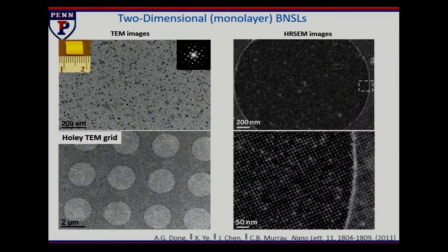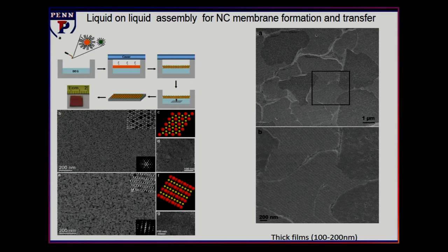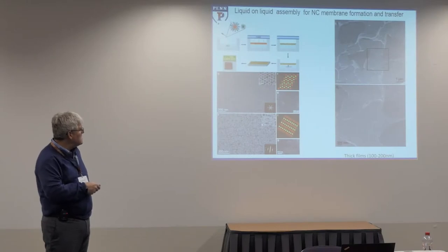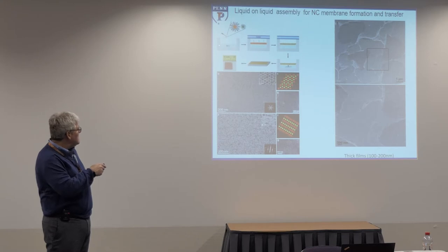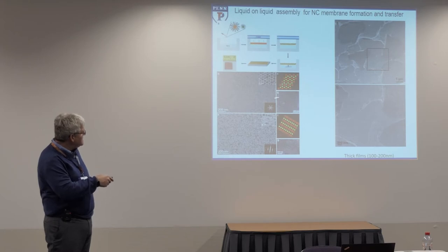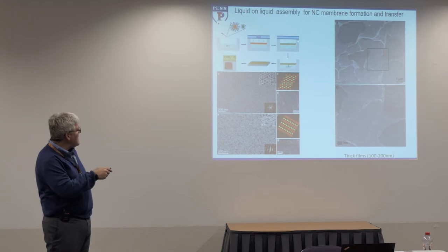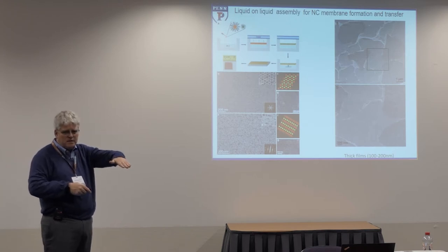All right. We make these materials in forms that are deposited on substrates or sometimes on liquid interfaces. The example that I'm presenting here is material that's been formed at a liquid interface. If I go back to this piece, there are some advantages in the ability to study the materials, but also to form the systems and then transfer them for subsequent integration for fabrication. If you make a layer on a liquid or, in some cases, a soft polymer, where the material will spread over the surface, wet, and then dry slowly, you can form these superlattice structures, but then you can lift off that material and stamp it and put it down in a different region.